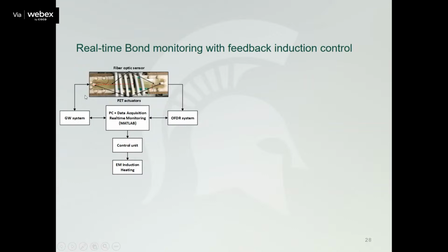So this is a design where you have a guided wave system which can measure the energy from the top substrate to the bottom, with adhesive in between, while at the same time we apply fiber optic sensors so you have an accurate temperature measurement. The PC plus data acquisition algorithms give you the real-time monitoring capabilities. Everything is written here in MATLAB, and of course it can be optimized. So you have the optical fiber measurement system and the guided wave system, and from this control unit you can control the EM induction heating, optimizing the heating and giving a better understanding and control of the adhesion condition here.